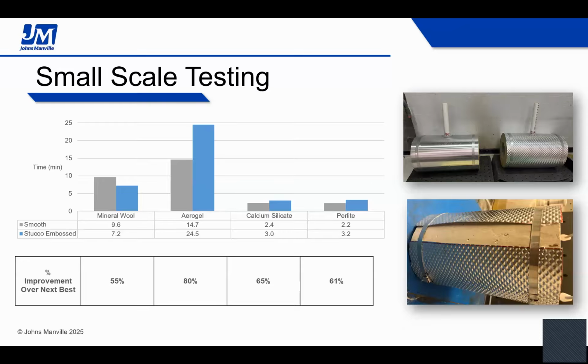Now here's the results with crossflow included. These results show the percentage improvement over the next best result. So this means that crossflow is 55% better than your stucco embossed over mineral wool. And then you have crossflow being 80% faster than aerogel being covered by smooth, 65% faster than smooth over calcium silicate, and 61% faster than smooth over perlite. So you can tell it really gets that water out of there as fast as it can.